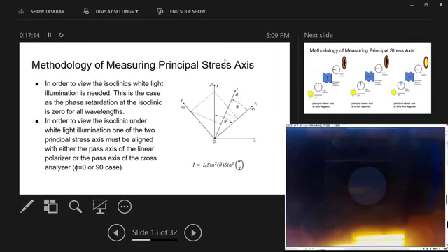That tells us that if at any given point in our object it's acting as what I would call a full wave plate, which is to say the light that comes out from that point is in the same polarization state as it entered, then we will return no intensity, because it'll be blocked by the analyzer because it's coming in normally polarized to that analyzer.